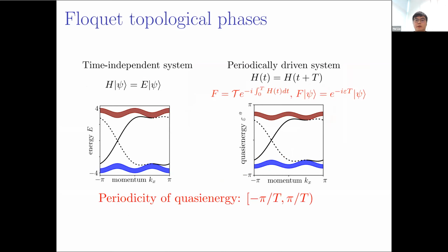Now we introduce this process to the Floquet topological system. For the Floquet topological phases, its time periodical driving system is dominated by the Floquet operator. Then instead of the eigenvalue for the static system, we would get a Floquet operator. The Floquet operator gives us a quasi-energy, which is periodic. So it gives us a fundamental domain at minus pi quasi-energy and pi quasi-energy. So in the Floquet system, we would have two different kinds of gaps, one at 0 quasi-energy, one at pi quasi-energy. For this figure, the 0 quasi-energy gap is topological non-trivial because it holds a pair of chiral edge states, but the pi quasi-energy gap is trivial.